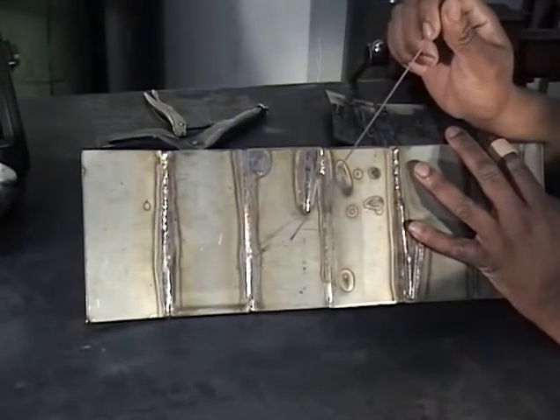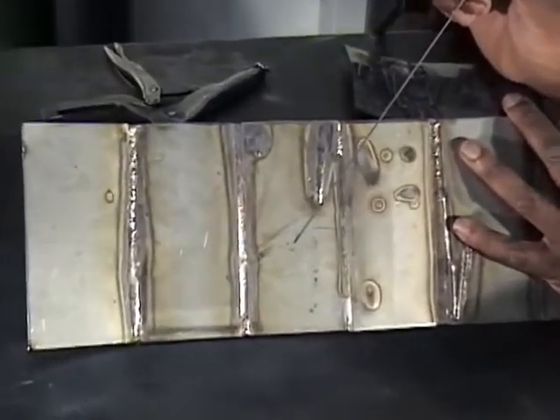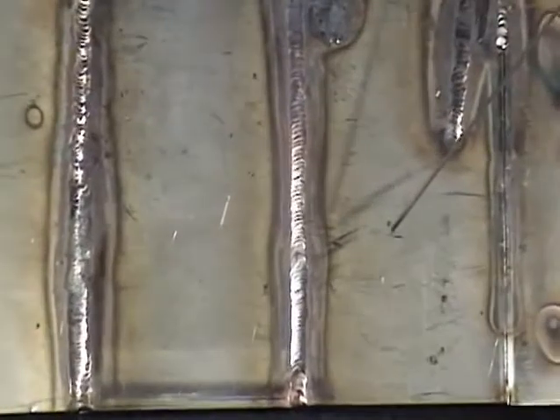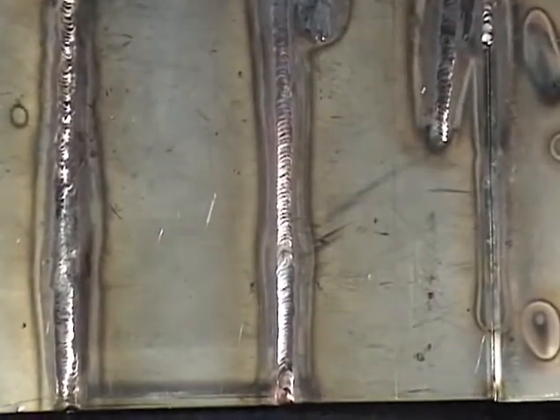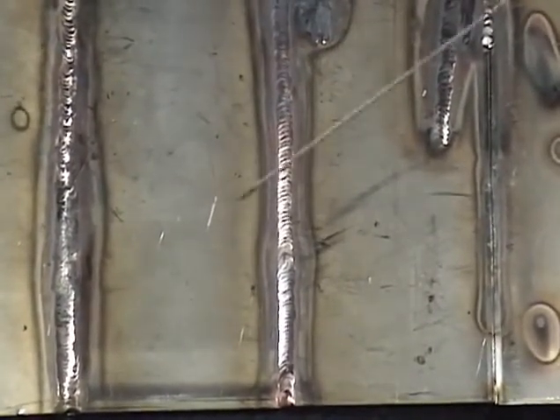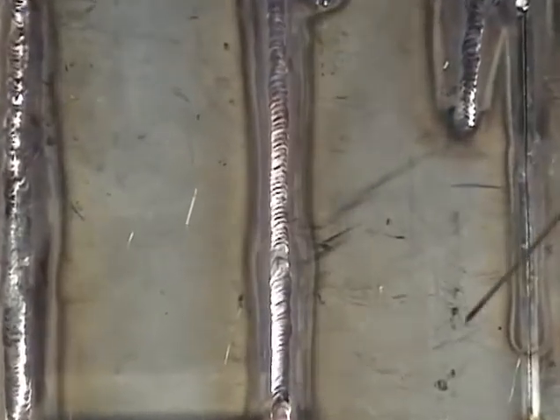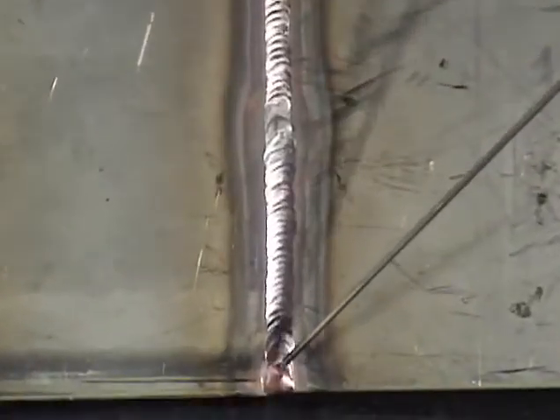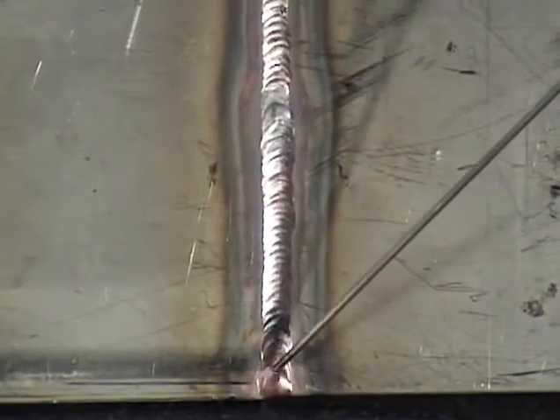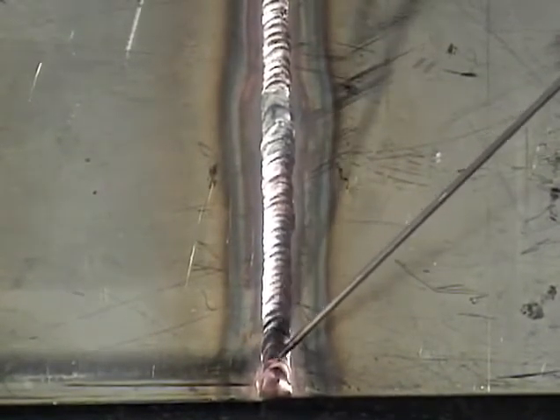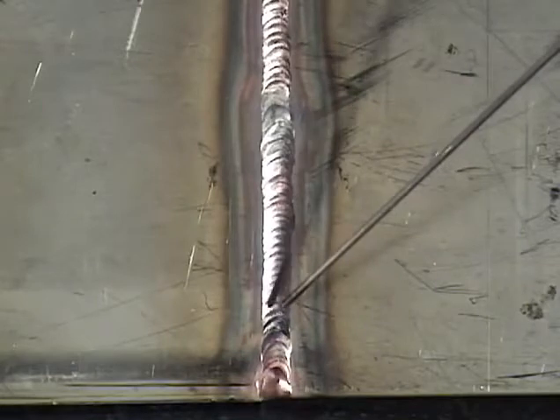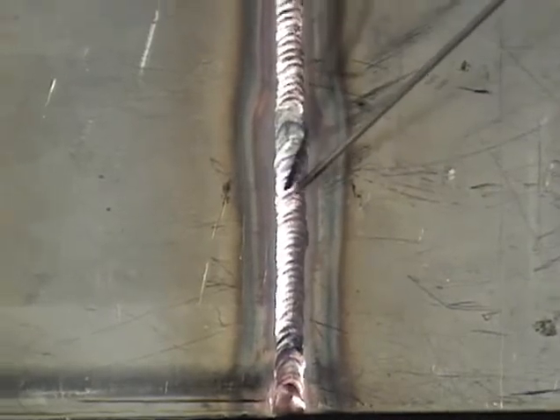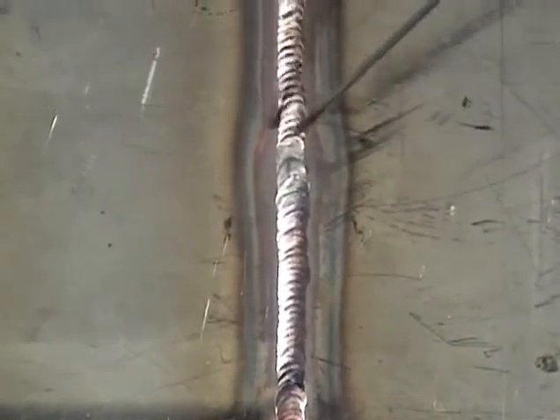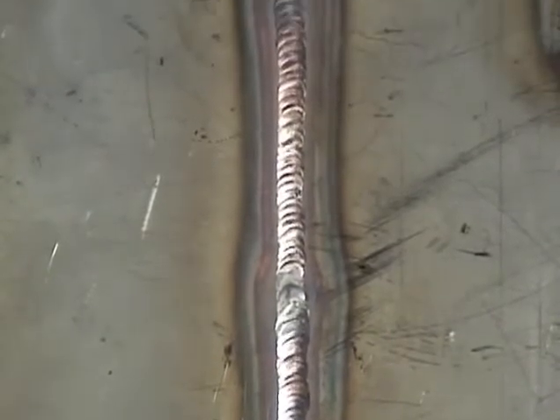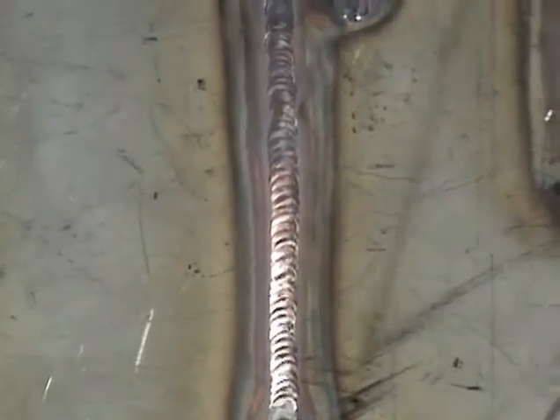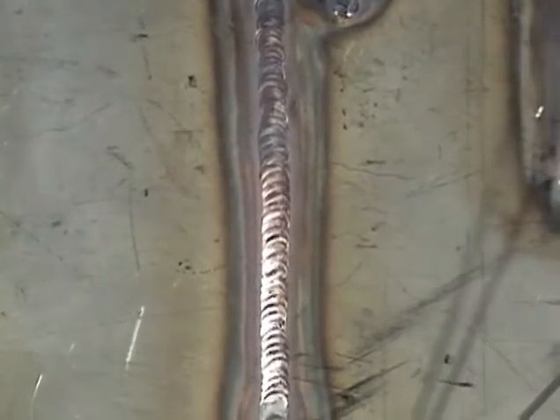Okay, we just finished welding our stainless steel butt joint out of 3/16 stainless steel. This is what a finished weld should look like. This was the start of the weld down here. We welded this in the flat position. This was the start of the weld where you're going to have greater amperage to get that to fuse. And then stainless steel, as it gets hotter, does not require as much amperage. But you're looking for nice colors, the reds, the blues, the straws, no blacks. Yeah, that's what you're looking for.